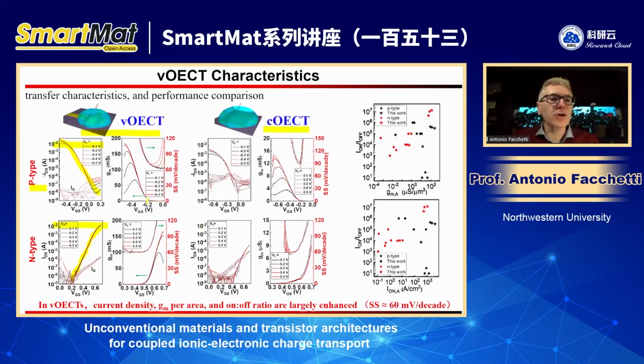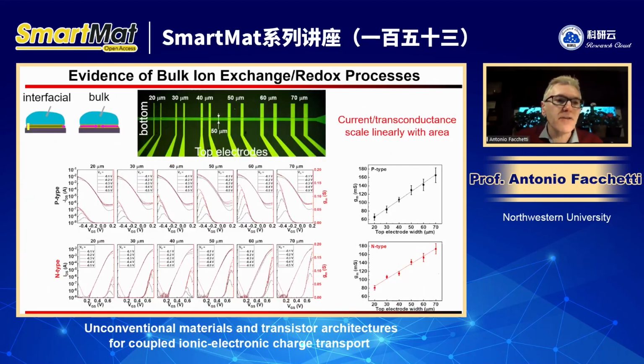Also, the question is, are you confining the ion only at the interface, or are the ions really penetrating through the bulk? In order to demonstrate this is a completely bulk process, these are different VOECT with different areas, but they have the same interface. The interface is the same in all devices, but the area changes. If you had only interfacial charge transport, you should get the same current in all devices. But what we see here is that the current increases linearly with the area. So it means it is a completely bulk transport. The ion really penetrates, although the film is only 100 nanometers thick.